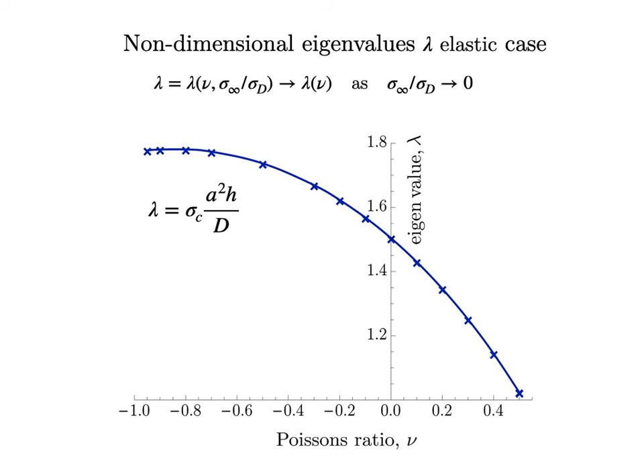the entire possible region, from Poisson's ratio equal to minus 1, when the material becomes unshearable and with infinite stiffness, to incompressible at the other end, 0.5. So normally your materials are usually placed between 0.2 and 0.4, and then the variation is not more than, well, some 20% or so. Not so bad as it looks when you look at the graph, though.